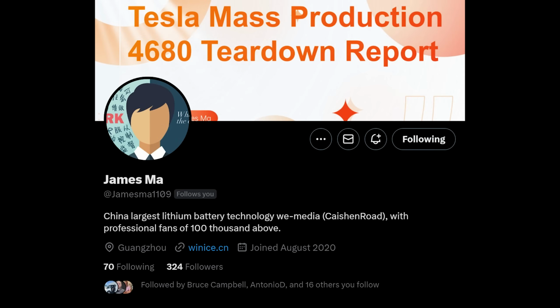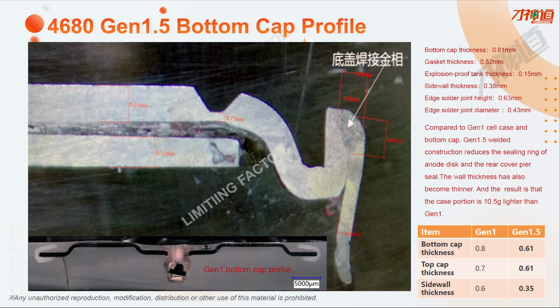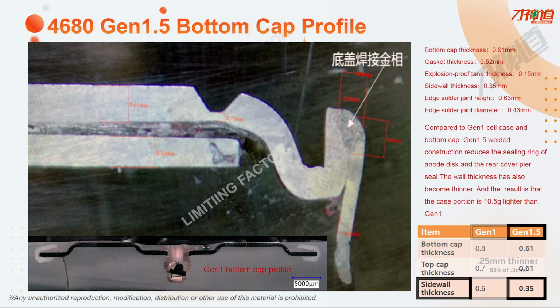However, I've since been in contact with James Ma of CaishenRoad. James is based out of China and does comprehensive battery teardown reports. His measurements, which were more thorough, showed that the Generation 2 4680 cell can, listed here as Generation 1.5, had a thickness of 0.35 millimeters. That would put the thickness reduction from the Generation 1 to the Generation 2 4680 cell can at closer to 0.25 millimeters, or about 83% of the 0.3 millimeters that I suggested 2 years ago.